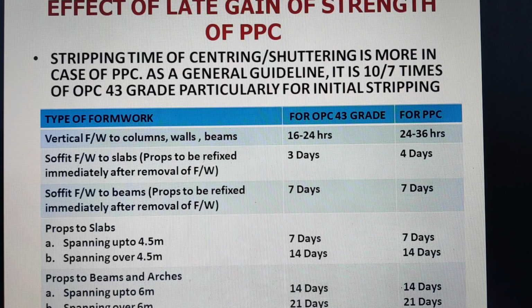So suppose vertical formwork to columns, walls, beams is to be taken out for OPC 43 grade between 16 and 24 hours. So it may be between 24 to 36 hours in case of PPC. Similarly, soffit formwork to slabs, if it is 3 days, then it may be 4 days in case of PPC. Approximately a factor which can be multiplied is 10/7. And we should remember that we are to remove the formwork for the curing. So this is the multiplication factor.